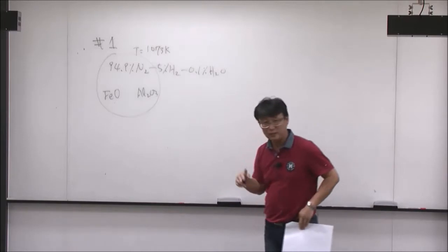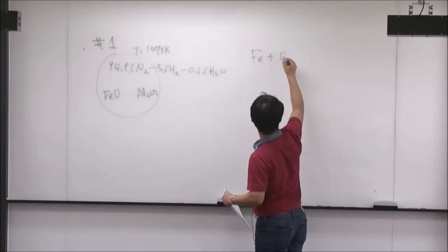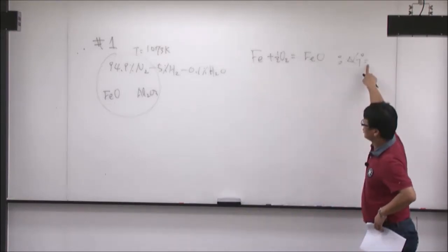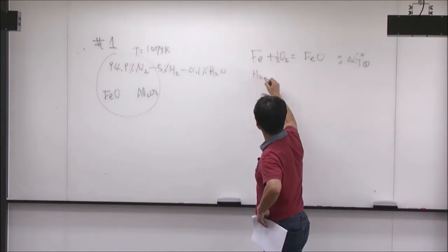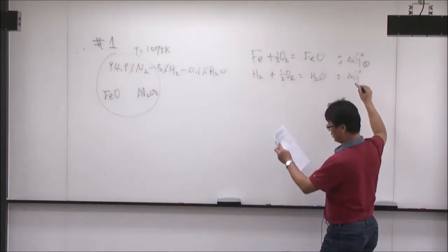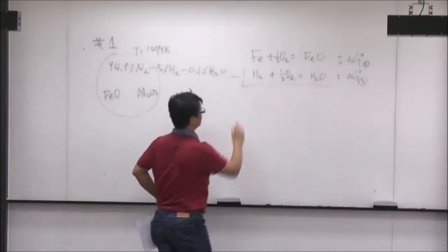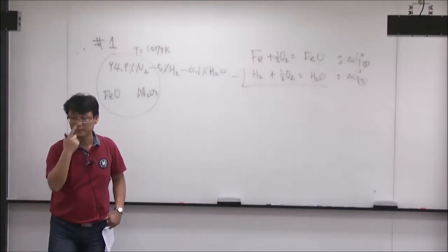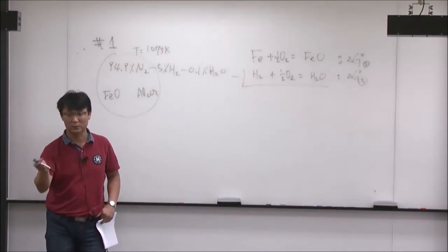There are two ways to solve this problem. One way: if you look at iron plus O2 — for example, Fe + ½O2 = FeO — I give this delta G0 of reaction. So you can put in the temperature and get the delta G0 of reaction number one. Then there's the last equation involving H2 gas. These give delta G0 for equations one through five. So you put them together to eliminate oxygen and make sure the hydrogen and water vapor gas phase species appear in the actual chemical reaction. Because you have the concentrations of the two different gas species, you can determine whether delta G of reaction is positive or negative.